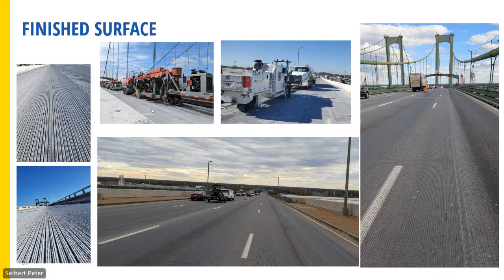This is typical, smoothness diamond grinding equipment. They do have to modify their operation slightly. We always recommend using the best blades that money can buy, and they run a little more water to make sure that they're flushing through the steel fibers that just kind of come out as part of that top sacrificial layer that's removed. But you can see here the nice corduroy finish, and the grooving gives it a nice texture. This was longitudinal grooved, as it was designed by DRBA and WSP.